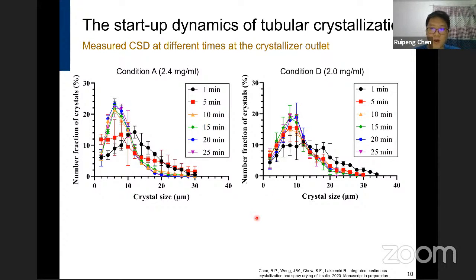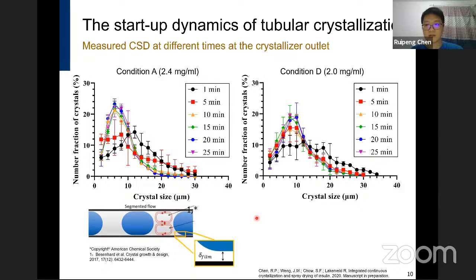The reason for the shift in the CSD, we think, can possibly be explained by the presence of the liquid film in the segmented flow, which is determined by flow velocity, the viscosity and other parameters. Small particles with a size less than the film thickness can possibly travel between slugs, and therefore the slugs that were formed initially have a reduced number of particles, and therefore the CSDs were on the right.